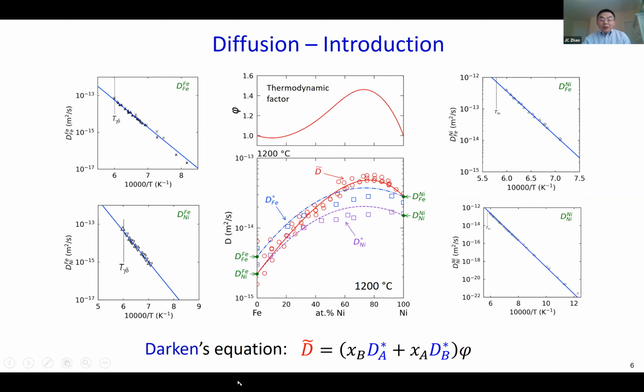So if you have an alloy and you do the same thing, let's say you put a nickel tracer, and then you get a diffusion coefficient of tracer, and this is the iron tracer diffusion coefficient, right? So if you plot the tracer as a function of composition, that's the dashed line, and then the red circles are when you make a diffusion couple, and then you measure using the Boltzmann-Matano analysis, you got this diffusion coefficient as a function of composition as well. So those are two fundamentally different kinds of diffusion coefficient, but they're related by the Darken equation, right?